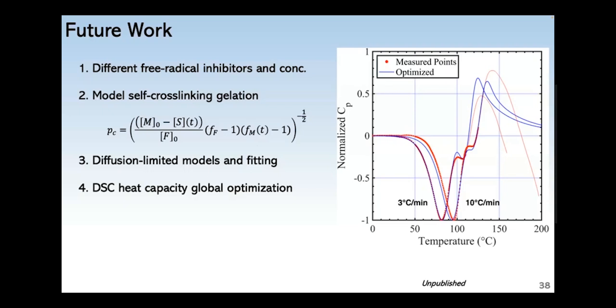Another thing you could do to study this work further would be to study the reaction rates but fit the data using diffusion limited models, which I didn't do. And then I completed some preliminary work by attempting a global optimization fit of the DSC heat flow data in order to back out the kinetic parameters for both exo and endo adducts, which I'm showing in the plot here. The blue lines are the optimized heat flow, and the red points and lines are the measured points. But it still needs some improvement. So this could be something else that could be done in the future.